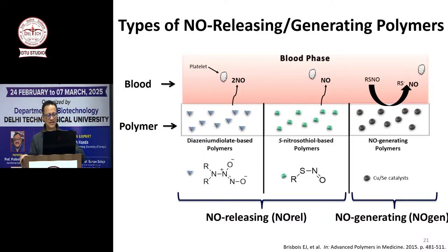Now, nitric oxide generating materials, or NO-gen, is when we put a catalyst in the coating, which can be copper or selenium, for example, and our blood has these packets, or RSNOs, or S-nitrosothiols, that carry nitric oxide. When this packet of nitric oxide carrying molecule comes in contact with this catalyst, it releases nitric oxide. So we are not relying on the coating that has a nitric oxide donor in it. We are relying on the nitric oxide packets present in blood, and our catalyst is converting that packet to nitric oxide release. Okay, so nitric oxide releasing materials, nitric oxide generating materials.